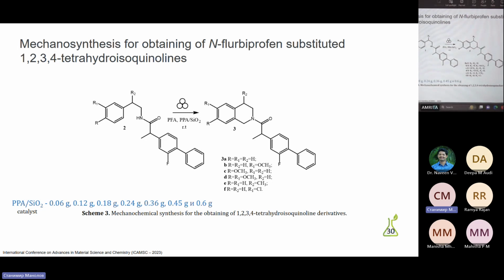The catalyst amount was systematically adjusted, ranging from 0.06, here given in blue, to 0.6 gram, specifically 0.06, 0.12, 0.18, 0.24, 0.36, 0.45, and 0.6 gram, as indicated here. Next to the reagents and catalyst, two metal balls were placed and the container was securely sealed to initiate ball milling. Under these conditions, encompassing the catalyst quantities of 0.06 to 0.45 grams, along with the experiments using pure silica gel, no observable reaction progress was recorded over time. That's why I give them here in red. It was only when 0.6 gram of the heterogeneous catalyst was employed that a complete and noticeable reaction took place, with reaction progress evident in all cases.